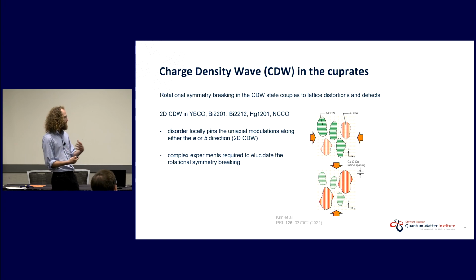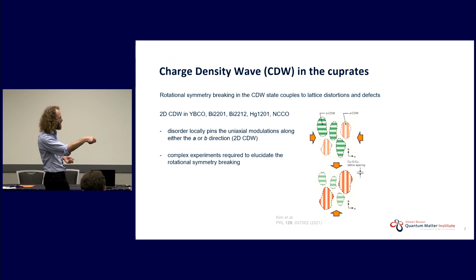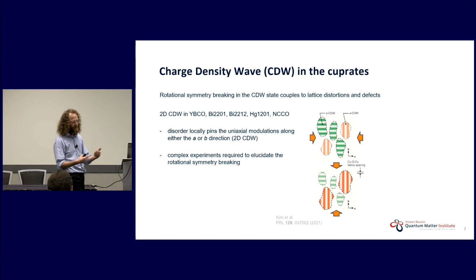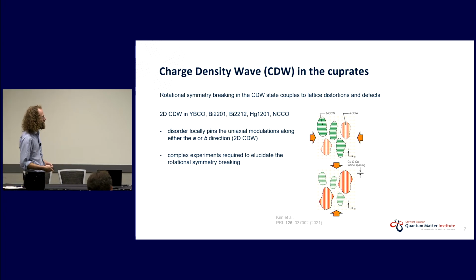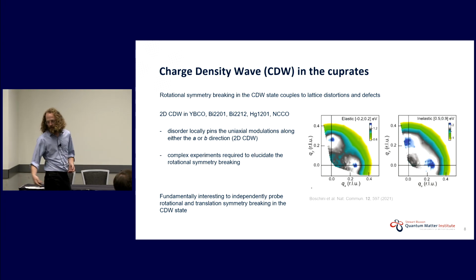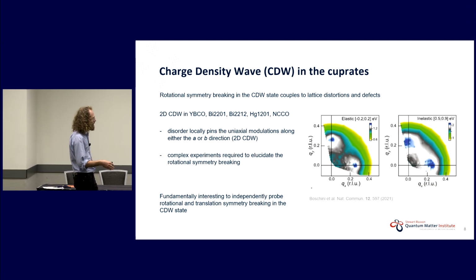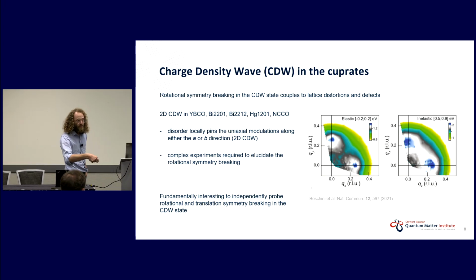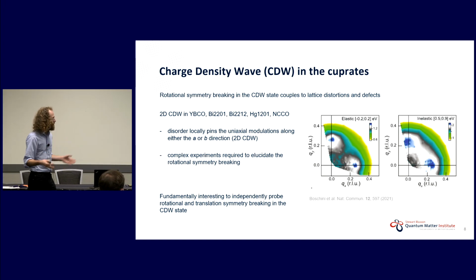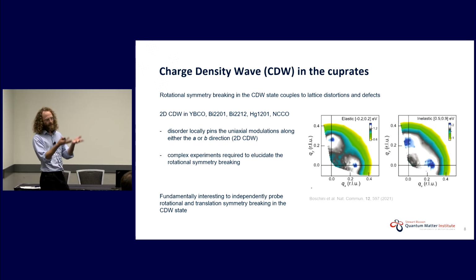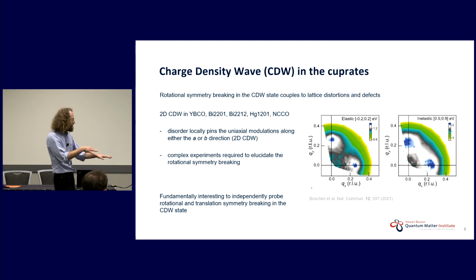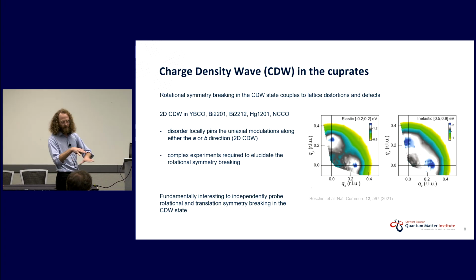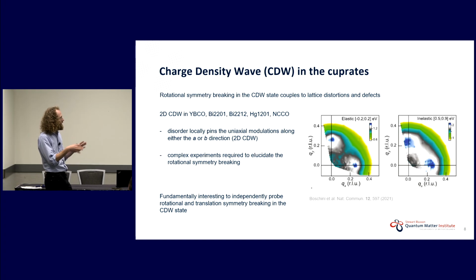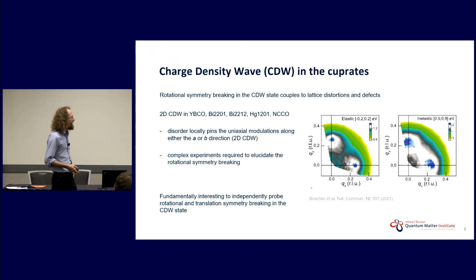And it can actually be quite complex, in a scattering experiment, to elucidate this uniaxial character. So Bernhard Keimer told us yesterday about these complex strain experiments where you're able to really get at this uniaxial character, but it's not always trivial. And in fact, there have been recent measurements by Alex and Eduardo, which have shown us that you can see charge density wave correlations in all directions, and Fabio, of course, in the copper-oxygen planes, actually showing us a heightening of the symmetry of the charge order with respect to the lattice. Now, of course, we don't know what the microscopic arrangement of those fluctuating CDWs is, but the point is it is fundamentally interesting to independently probe rotational and translational symmetry breaking in this state.